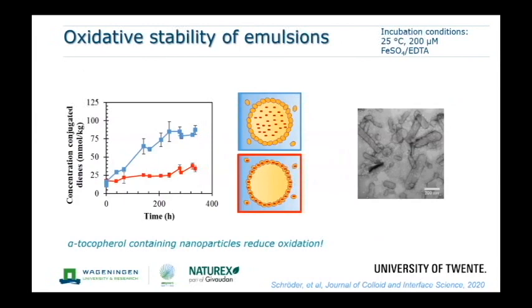We can also use nanoparticles to make emulsions physically stable. On the right here, you see solid fat particles that we have made, and these solid fat particles would also occur in cream, for example. What we've done is make two different emulsions. In one emulsion, the top one, we put antioxidant in the oil, and then we stabilized it physically using these particles. In the bottom one, we added the antioxidant to the particle and then stabilized the emulsion.